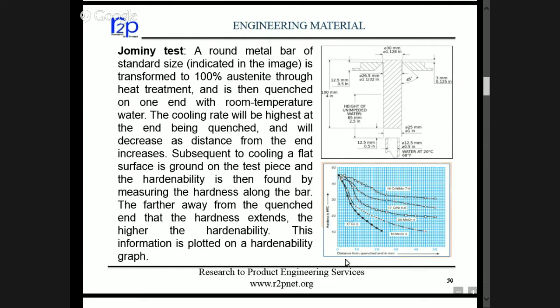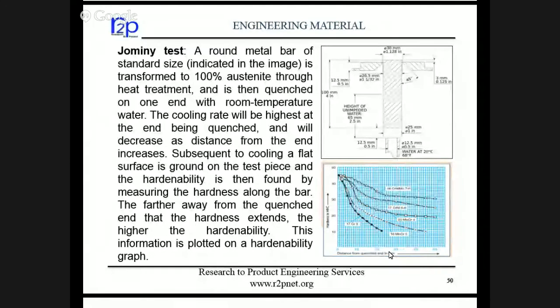And here in this graph is shown the distance from the quenched end, 0, 10, 20, like that. So if we see the lowest curve, 17CrNi3, right? There is no manganese, there is no moly or nickel in this. It's a low alloy steel, you can say. The depth for the same, for hardness of 30, the depth is going only up to 7-8 mm, right? But in case of a highly alloyed steel, under similar conditions of quenching, the depth is going up to, you can say, 30 to 40 mm.